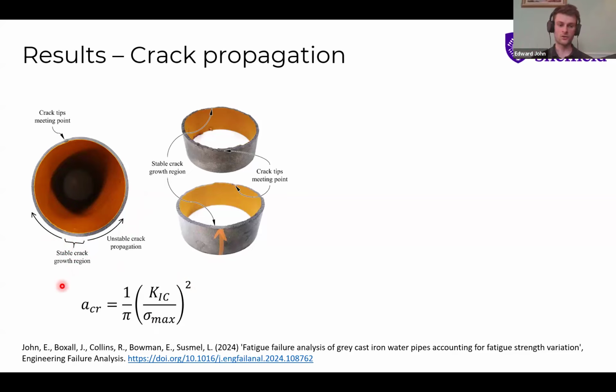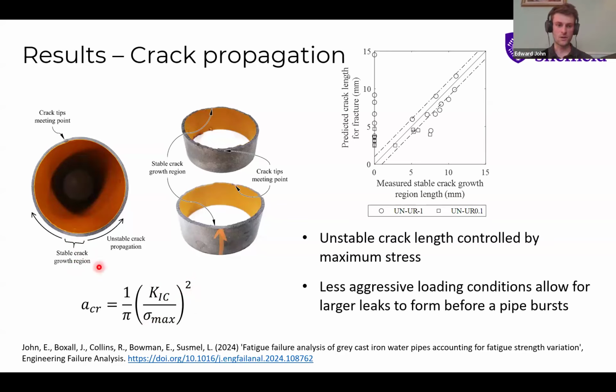So according to classic fracture mechanics, we should be able to predict this stable crack growth region using the equation down here, which is saying that the length of that maximum crack size is a function of the fracture toughness and the maximum stress that the pipe experiences. So the crack grows by the variation in stress, but the idea is that the maximum size of it is limited by the maximum stress. So from measuring all of these stable crack growth regions and plotting them against the predictions of this equation, we found generally a pretty good agreement.